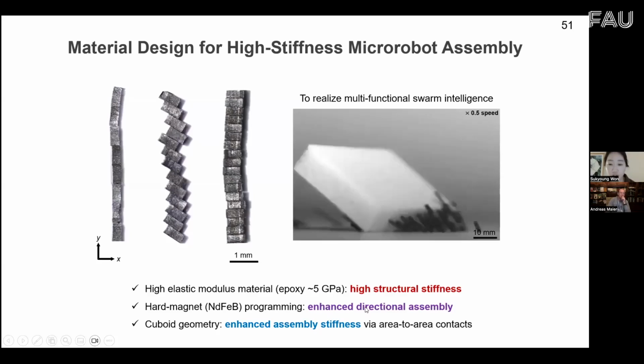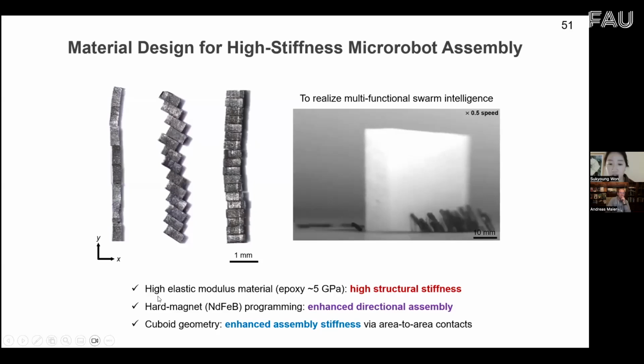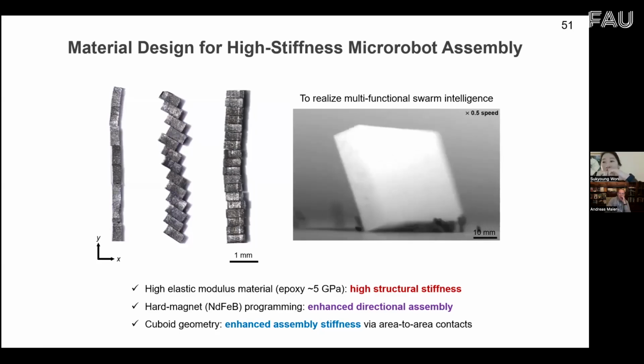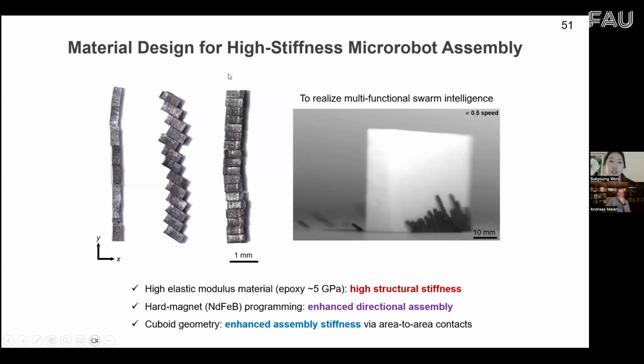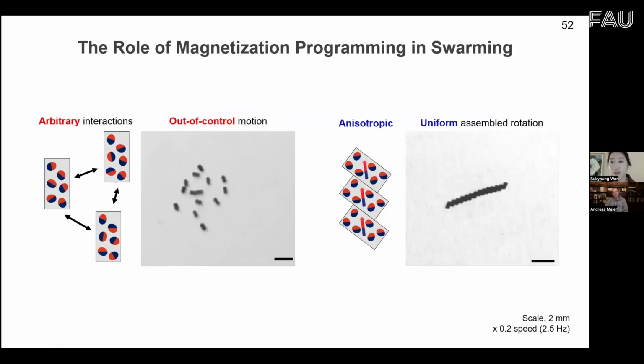And also this directional assembly can be enhanced by the magnetization profiles, and this structural assembly is increased by using the cuboid geometry of the microrobots, because spherical robots are usually assembled through point-to-point contact. But when we use the two-dimensional interface between the microrobots, we increase the assembly structure of the microrobots.